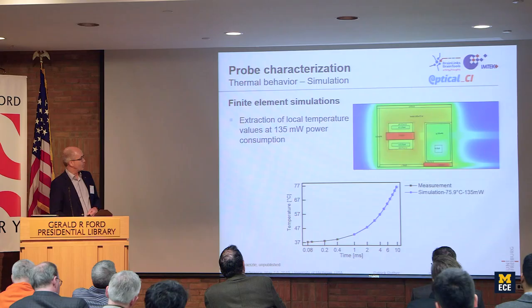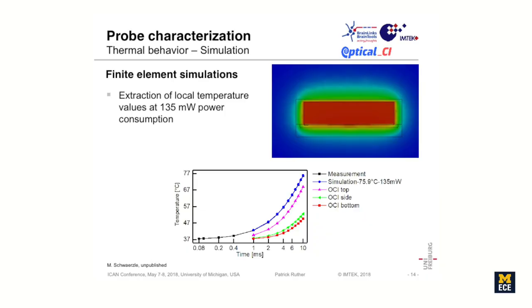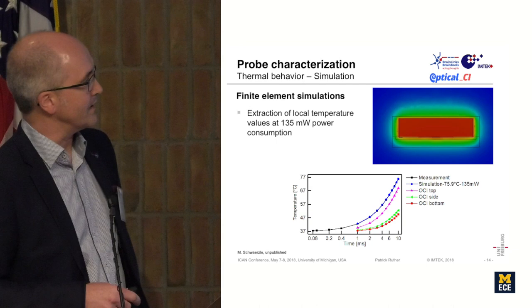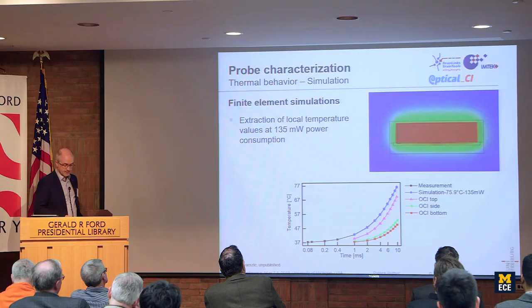And when we take a completely encapsulated probe and we look at the temperature at the top and at the bottom, still we see these huge temperature increases if we work with 10 milliseconds at a huge electrical power of 135 milliwatts. So this is for sure nothing that we in general use in the experiment, but it tells us what the temperature evolution is.